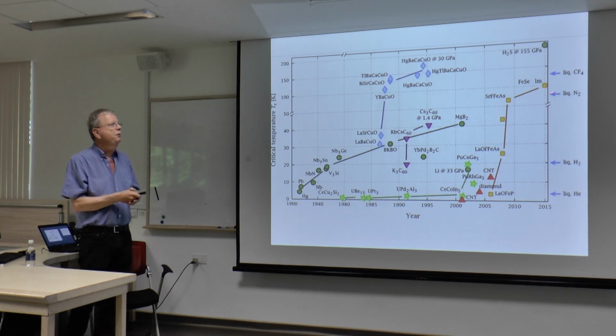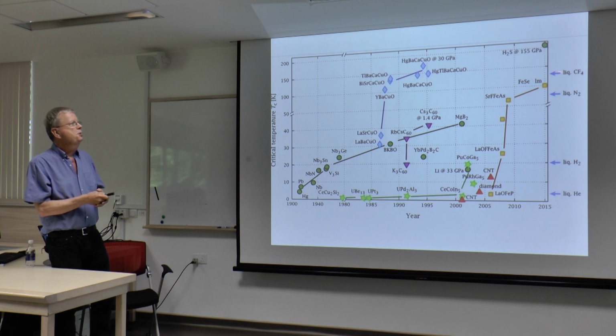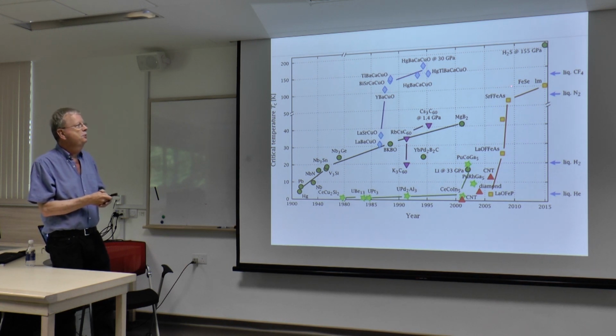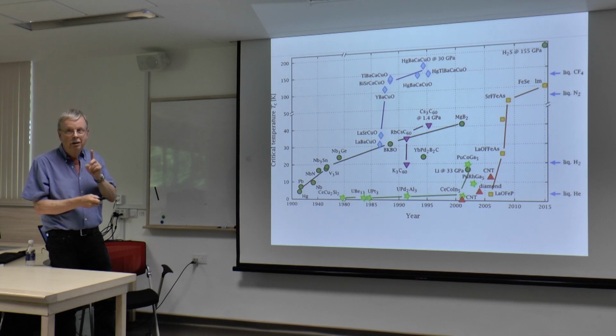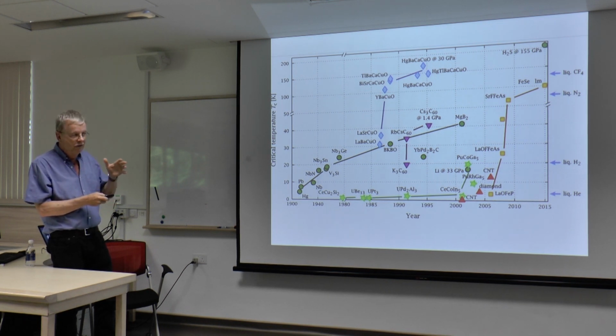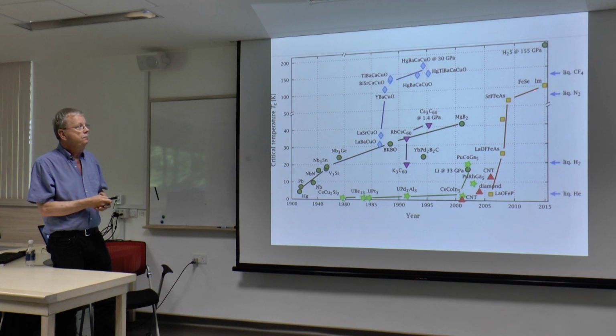I am informed by a theory colleague that I shouldn't say that this is a known fact. Only one group has gotten to 106, I think. Other groups are talking about 60 and 70 Kelvin. But it is without doubt that if you take this 8-degree superconductor, which would be down here somewhere, and make a monolayer, not a bilayer, a monolayer on strontium titanate, and on a few other dielectric substrates, it doesn't just have to be strontium titanate, you get around 70 to 100 Kelvin.